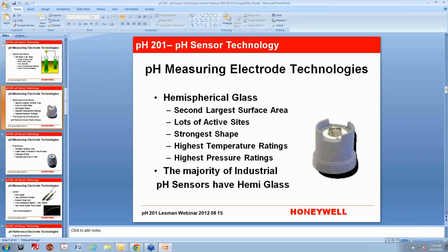is the hemispherical glass. This is a pretty decent picture of hemispherical glass. So basically it's a half of a ball or a half circle, and it is welded or annealed to, again, a glass stem. It has the second largest surface area, so it still has a lot of active sites, but not as many as the spherical glass. This is the strongest shape, and the reason it's the strongest shape is because if you think about this half ball being welded to a hollow glass stem, that weld angle is 180 degrees.